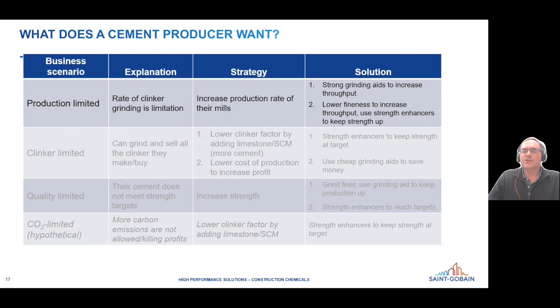But to show how this situation is actually a little more complicated than that, the other thing we talked about is the effect of fineness on the grinding efficiency. So the finer you grind your cement, the longer you have to grind it to get there. So one way to make the throughput of your mill faster is just to grind it less and just have a lower target fineness for the cement. Problem there, of course, is that you then have lower strength development, particularly at early ages. And you could counteract that with a strength enhancer. So in this roundabout way, a strength enhancer actually helps to increase the production rate of the mill because you can use lower fineness.